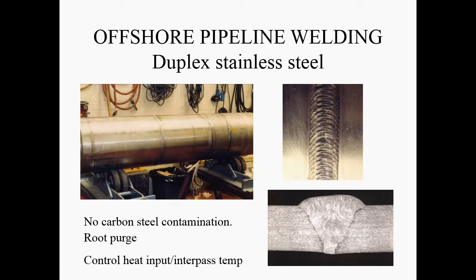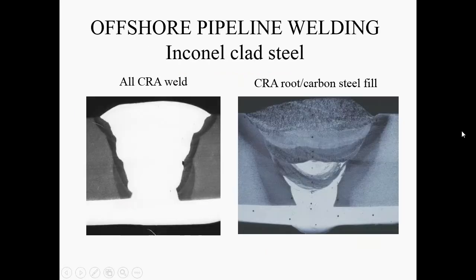That's why we need to keep the interpass temperature within these limits in order to make sure that we don't have a very slow cooling rate, to avoid the carbide precipitation. Because remember, what's the effect of carbide precipitation? It will lead to depletion of chromium, and consequently the corrosion properties will suffer.